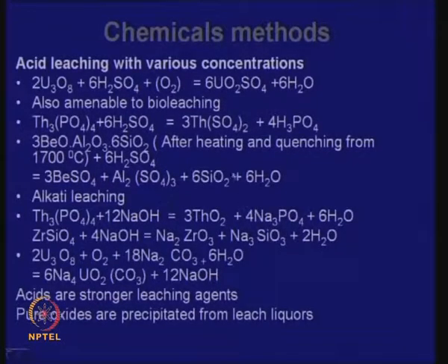In the case of uranium, for example, U3O8 is the oxide you are aiming at. It can be leached by sulfuric acid, taken into solution as a sulphate. Incidentally, this is also amenable to bioleaching.